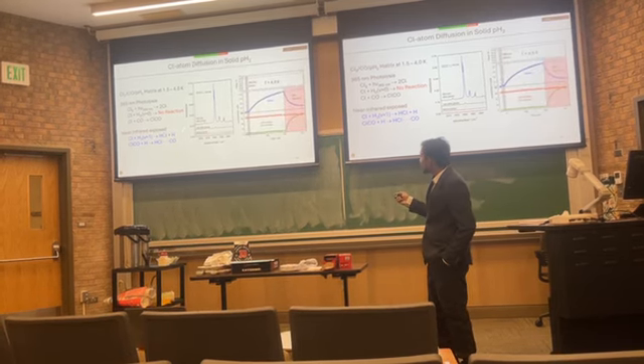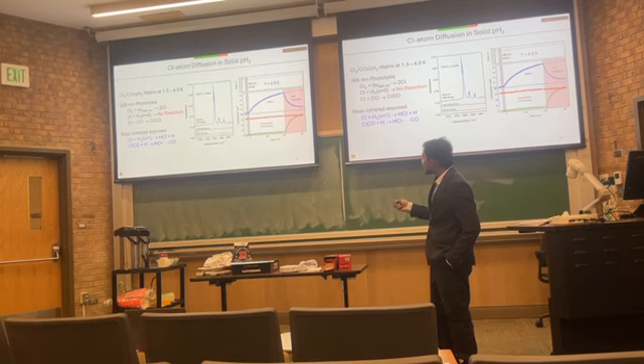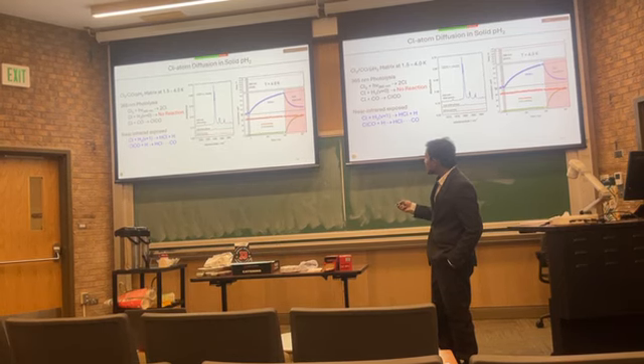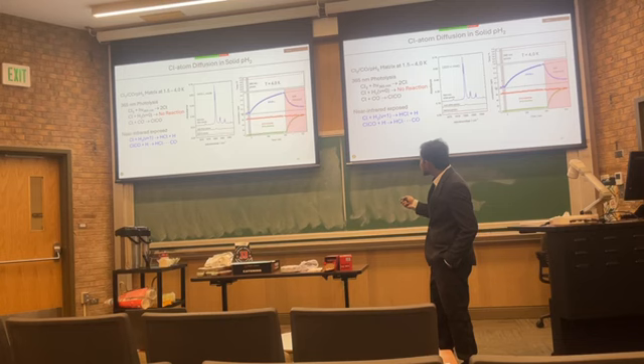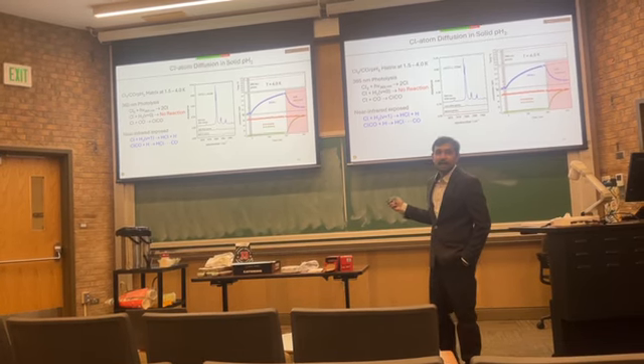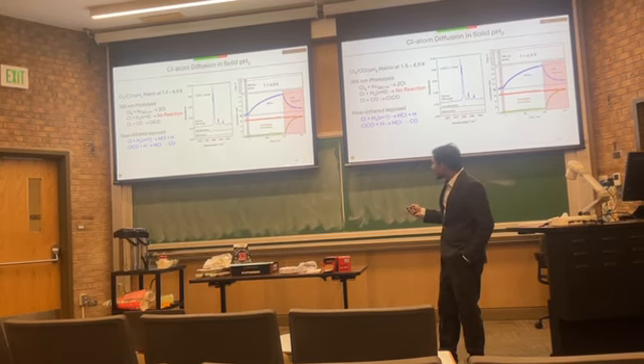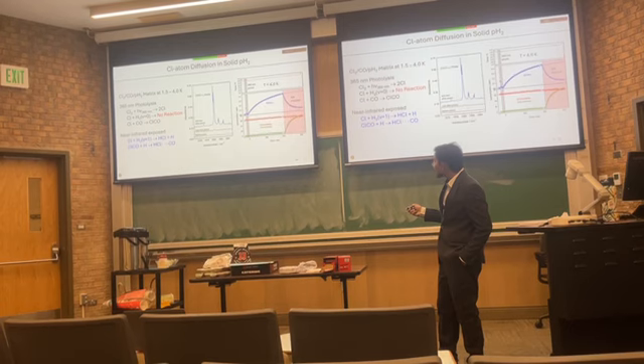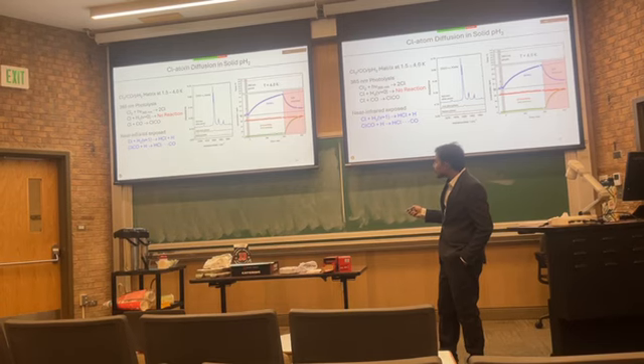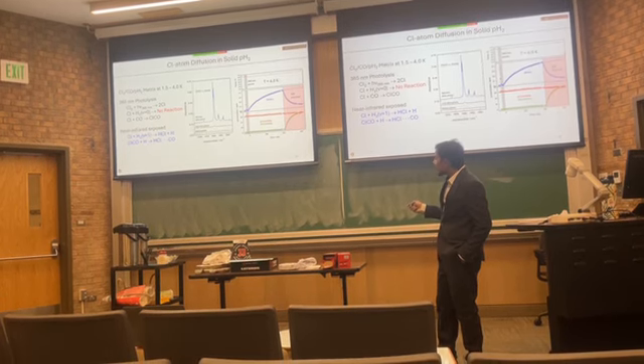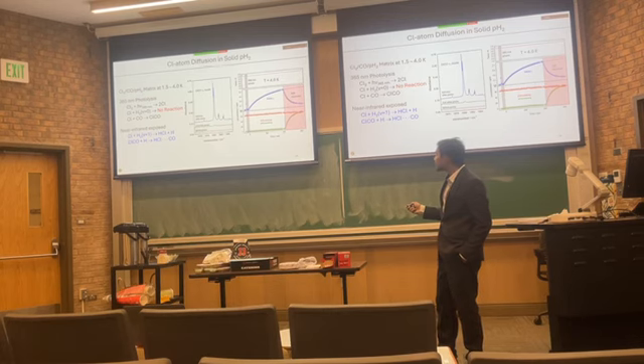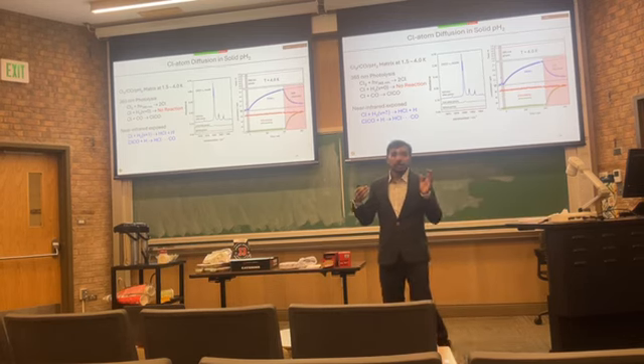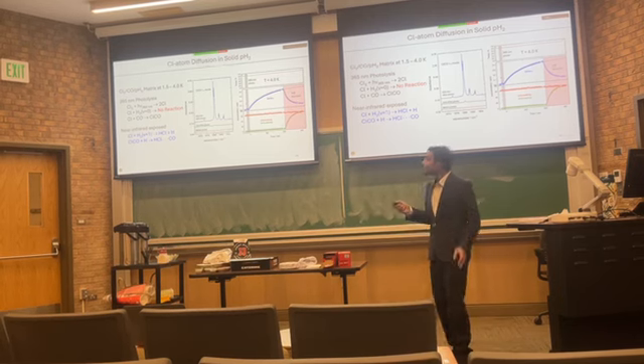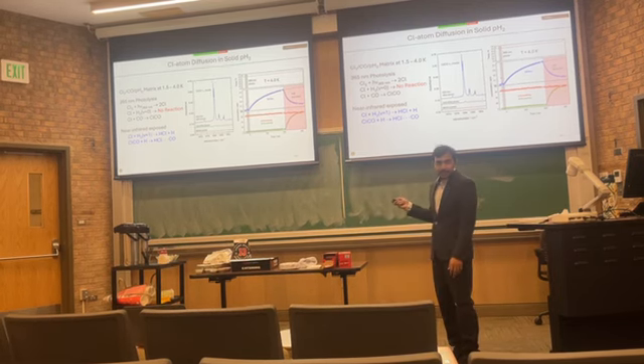We did this experiment at 4 Kelvin. This is 365 nanometer photolysis, and this red bar is NIR exposure. First let's look at HCl, this bottom one. There was no HCl until we exposed it to near infrared. This is CO. CO is not reacting a lot, that's why our CO is almost constant.